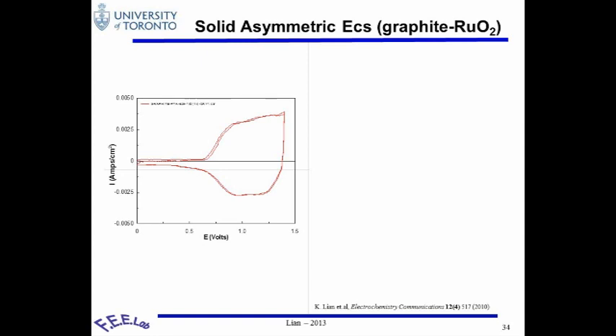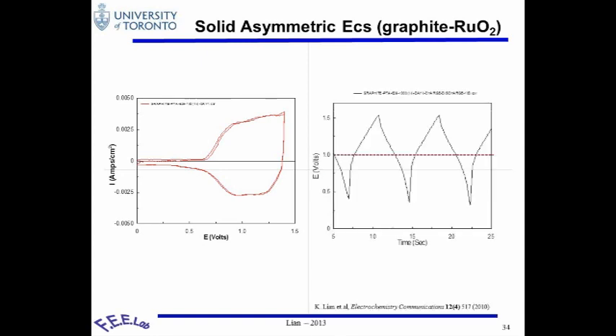Now we push from 0 to 1.5 volts. This is actually a charge-discharge curve. What's interesting is you can see the capacitor behavior up to about 1 to 1.5 volts, and then it goes down to have a very severe discharge here.